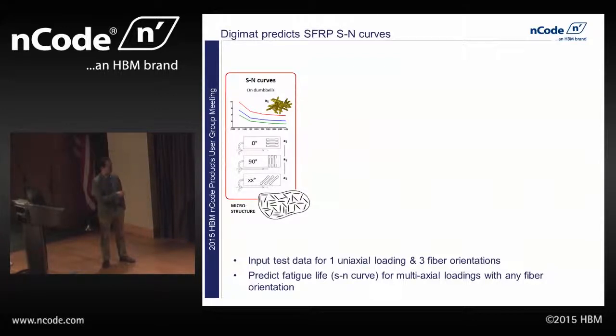So up at the top here, you have this 0-degree curve. It's obviously the most durable material since the fibers are mostly aligned in that direction of loading. And then down here at the bottom, you've got this 90-degree curve where the matrix is taking most of the load, and it's the least durable scenario. And then you have a bunch of other scenarios that can fall in between.